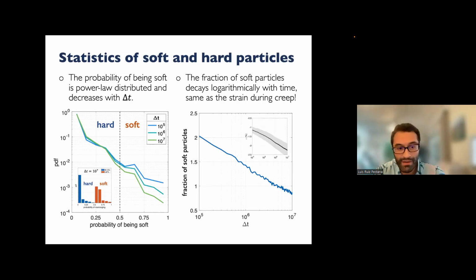So if you plot the fraction of soft particles, as we have defined them, as a function of time, you find that their number also decreases logarithmically in time. This is exactly how the strain decreases in primary creep. So what this suggests is, again, it's not a proof, right? But this suggests, and we are trying to find ways to prove it, that the soft particles, even though they are less than 5% of the system, sometimes much less than that, here the fraction of particles is 2%, seem to be controlling the creep response, the creep rate of the system, the deformation rate of the system.